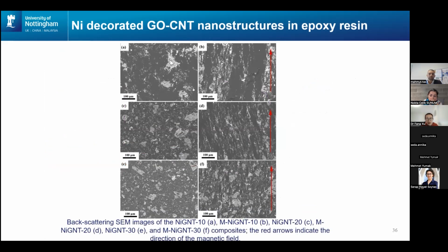So this is the SEM. We have also prepared a reference sample. On the left are samples of randomly distributed nickel GNT reinforced epoxy without application of a magnetic field. On the right is with a magnetic field applied. This red arrow shows the magnetic field direction. We can see there is a trend of alignment for the nickel GNT structures within the material.